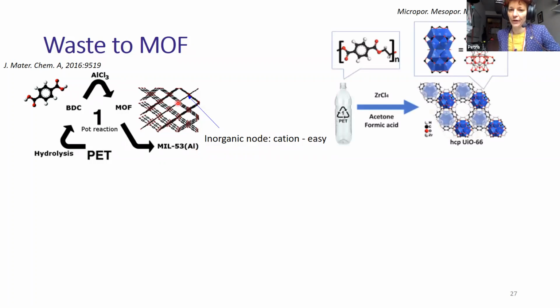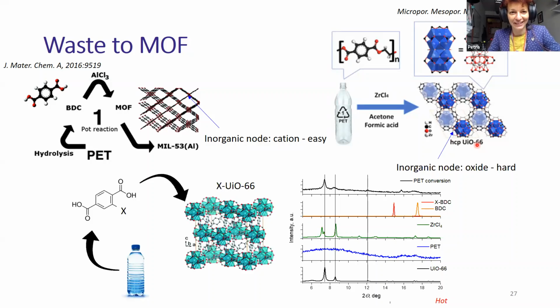In the case of when we want to make this UiO topology out of it, previously it's been shown that you can only do it in organic solvents. And recently I've had a project student who also, well, at the end I ended up doing this because of COVID, but we managed to show that we can use PET plastic as a precursor, and in a one-pot mechanism we can convert it into the UiO structure, while at the same time functionalizing the linker. And this is just to show that the UiO structure is formed.